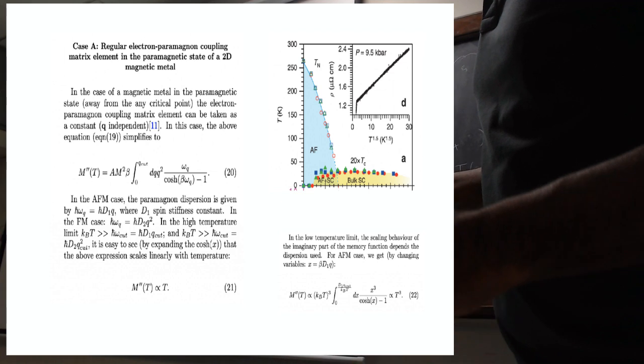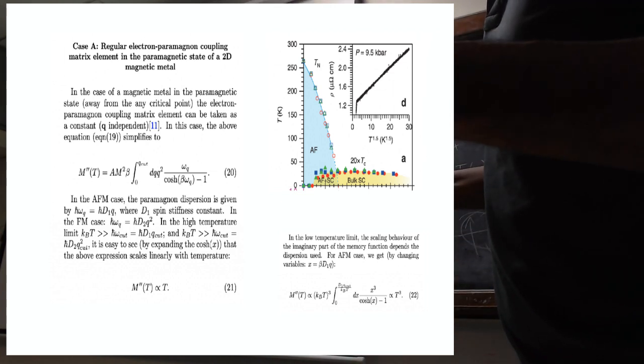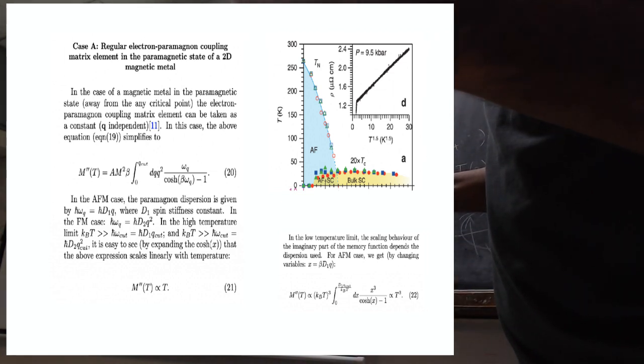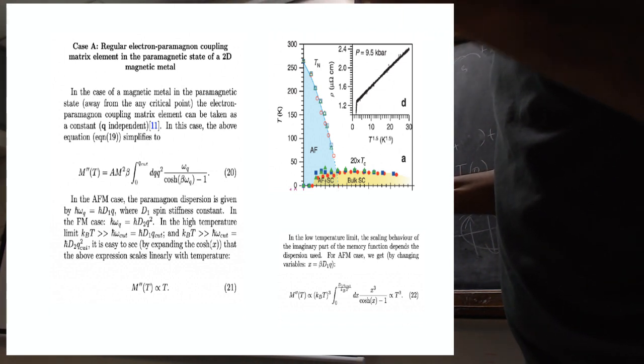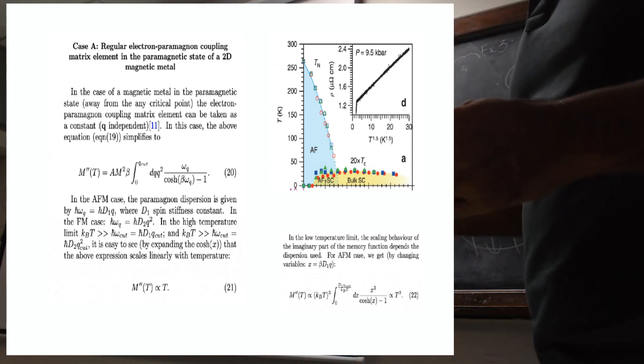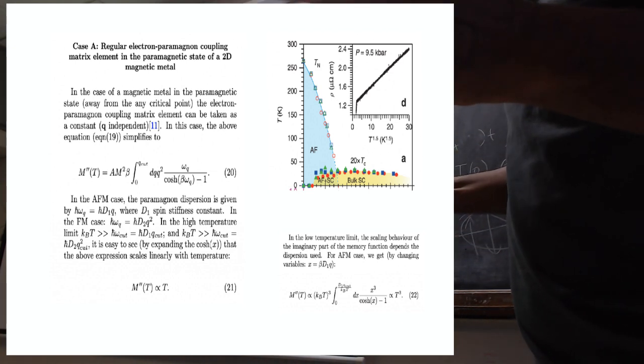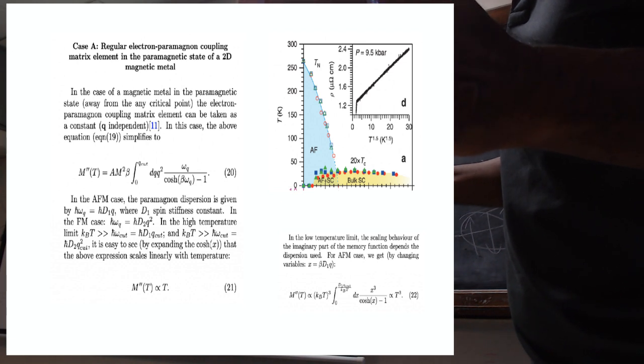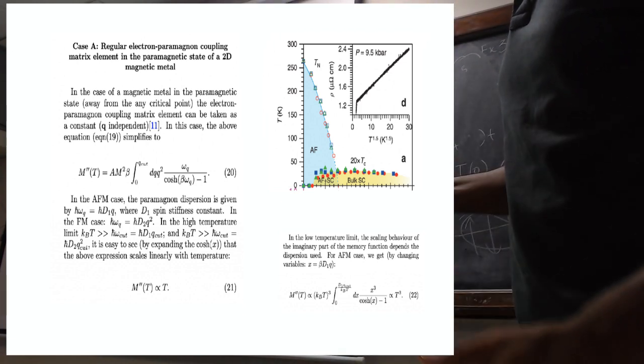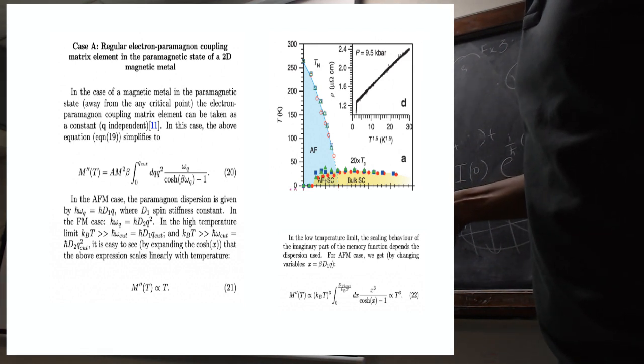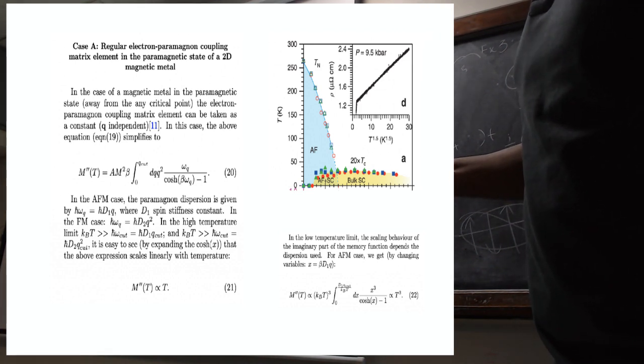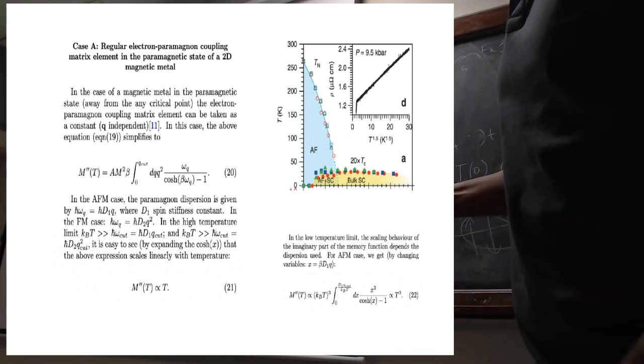So if you have the antiferromagnetic case, the magnonic dispersion is Q linear, but in the ferromagnetic case, the magnons go as Q square. And the high temperature limit is T linear. You can take the high temperature limit, and it can be very easily simplified. For the low temperature limit, you can just put beta omega Q as X. You can simplify this thing.